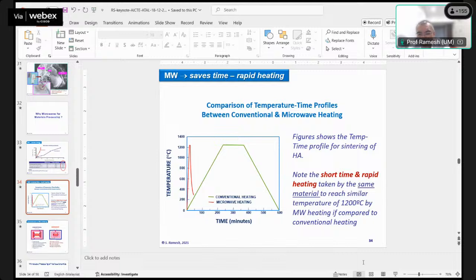So as I said, for research purpose it's nice, but of course for commercial you would need a proper microwave furnace. So I have a proper 6 kilowatt microwave furnace. It's a big furnace with which we do a lot of microwave work. This diagram shows the time taken, a fraction of less than 45 minutes. You are able to obtain hydroxyapatite that has similar density as the one that is sintered conventionally, which typically takes more than 24 hours.